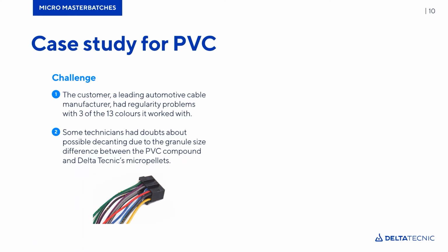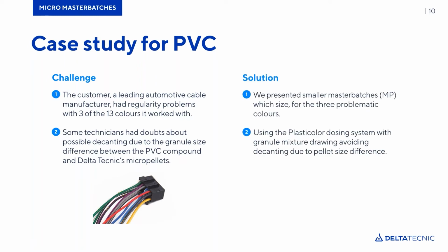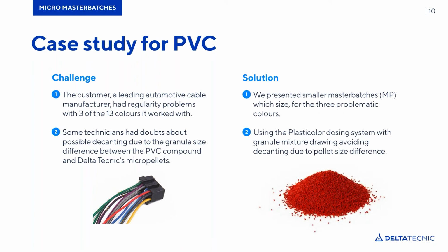So here, and it's very simple. Here we're talking about a global automotive wire manufacturer with factories all around the world, with headquarters somewhere in Europe, but playing all around, also in North America. And this customer had color regularity problems with 3 of 13 PVC based cables. And here we face the situation of some technicians having doubts about switching to smaller pellets because of the problem that I explained just before. However, we presented the smaller sized batches, the micro pellets in this case, and using this Plasticolor dosing system, with this mixing unit that I just presented, avoiding the effect of decanting due to the pellet size difference.